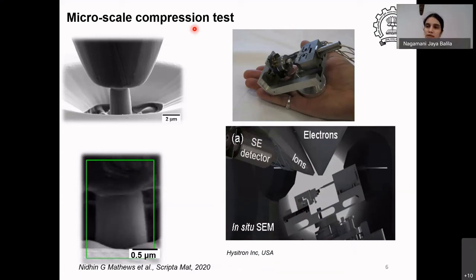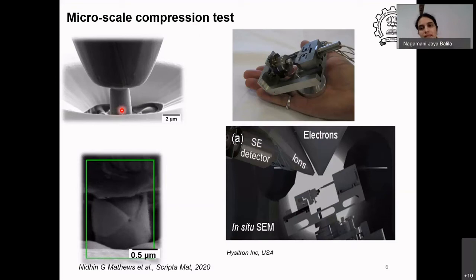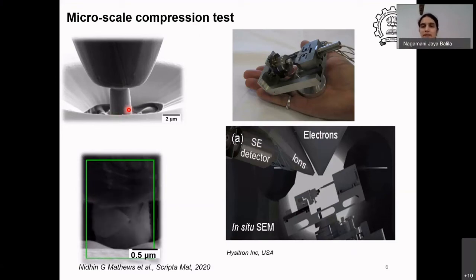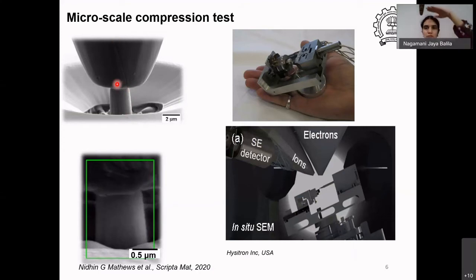Aligning the sample and pulling it straight is a difficult task, and that's why we go for the compression test — a reverse test which will give more or less the same yield strength for most materials. This is a single crystal of barium titanate, which is an oxide crystal — it's a ceramic, but in compression it will undergo deformation, whereas if you pull it in tension it would have just broken like chalk. This is the pillar we are talking about, and there is a punch which is pushing the pillar down and we are going to measure the response.